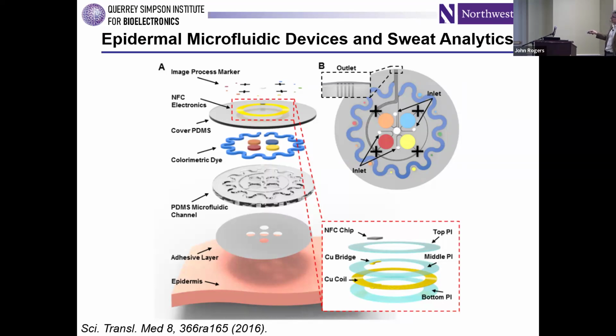It's a closed microfluidic system, but with openings in the backside to define inlet ports. And those inlet ports can be aligned to holes cut into a bilayer biomedical adhesive that bonds the device to the skin. So as the eccrine sweat glands activate, they push sweat up through these openings into the inlets and then through this network of microchannels and reservoirs where we can capture and store the sweat for biochemical biomarker analysis.